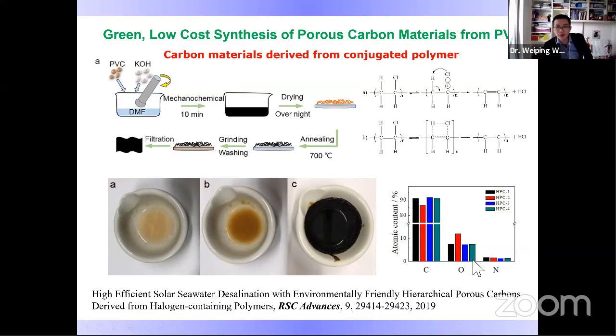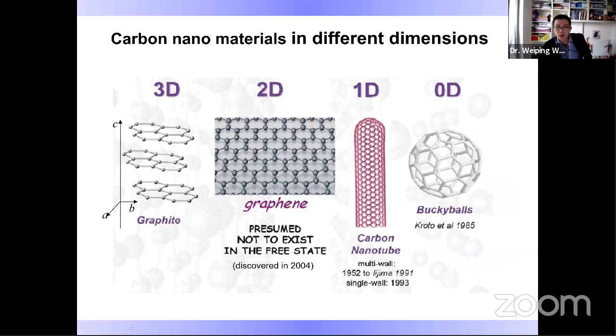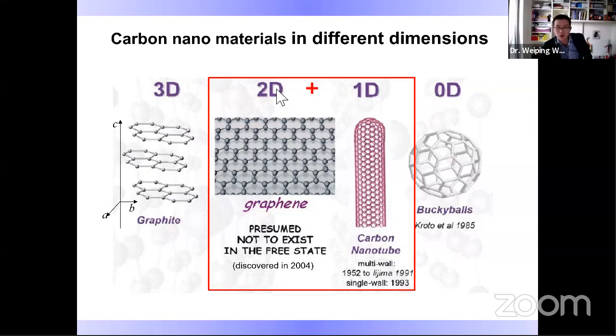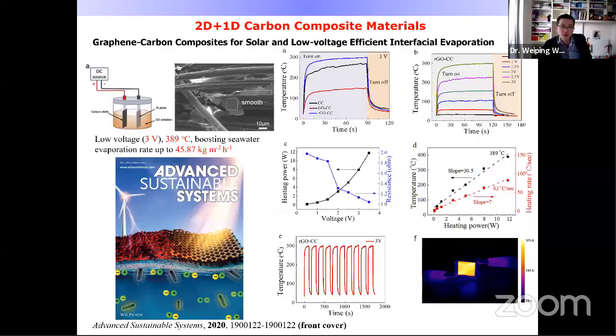Several related works are about the dimensionality of nanomaterials: 0-dimensional, 1-dimensional, and 2-dimensional. When we combine any of these materials together, like 1D with 2D, we can form a 1D and 2D composite structure, a carbon-carbon composite structure. By electroplating or reduction of graphene oxide, as you can see from the SEM imaging, the graphene flakes have been successfully attached to the 1-dimensional mesh of this carbon micro and nanostructure.